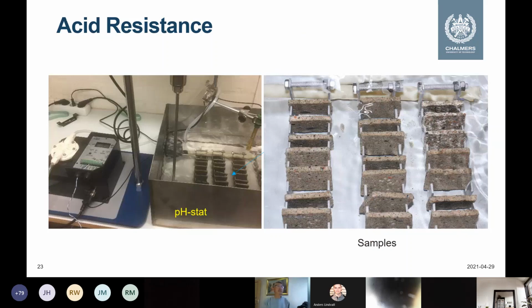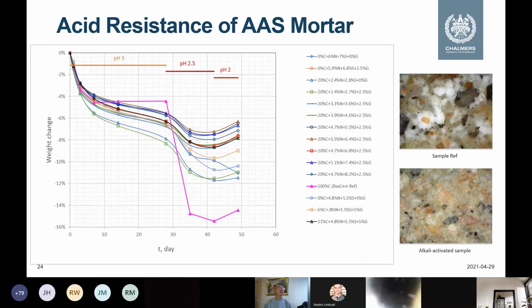Then about acid resistance, so far there are no standards to test the acid resistance. So we tried to use this pH stat to keep the acid constant and then measure the weight loss. This is our first trial for the mortar specimen. So this is the result. You can see in the beginning we set pH 3 because I heard that from wastewater normally it is pH 3. So we tested with pH 3. Then we got this Portland cement without weight loss. So we found that the Portland cement surface contains so many white deposits. I believe that is gypsum. Then this gypsum will absorb water. So this is why we cannot measure the decrease of the weight.